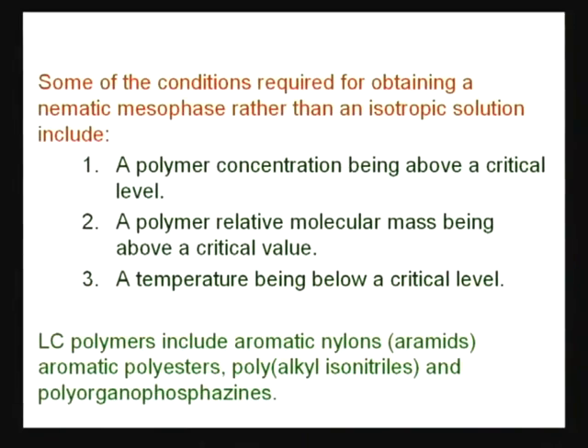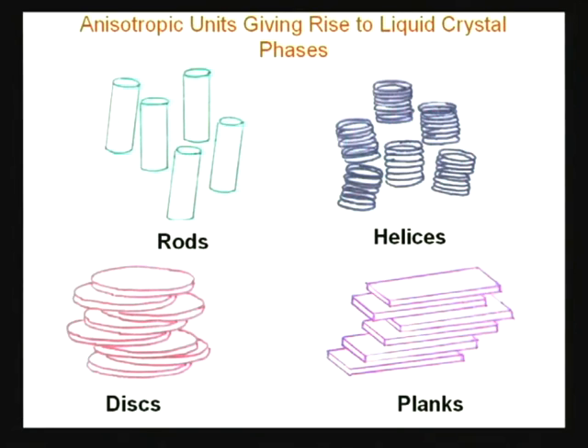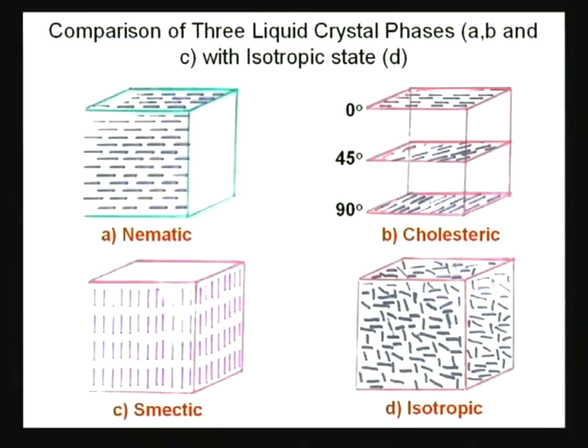What I want to show, look at here, anisotropic units giving rise to liquid crystal phases. Those anisotropic units which may be present in polymer backbone, that may be rod like shape, helical shapes, or disc type shapes, or plank type shapes. Molecular assembly like this, in helical, rod like, or disc, or planks. So, that gives you liquid crystalline behavior. Now, you see comparison of three liquid crystal phases: nematic, smectic, cholesteric, and isotropic.